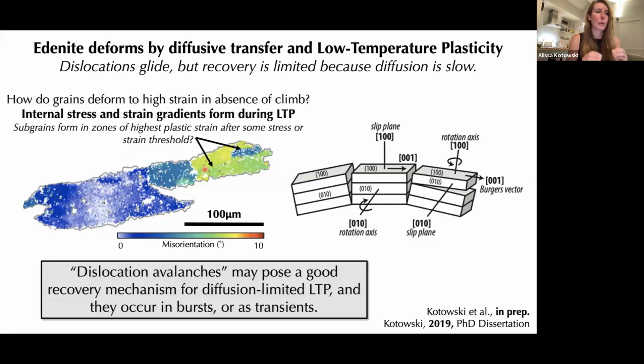So what this means ultimately is that we will have an imbalance in the number of dislocations coming in versus the number of dislocations going out. If it's hard for dislocations to leave, then they will come in, they will glide, they will hit each other and tangle, and you will actually create more internal stress and strain gradients as a function of the inability for dislocations to leave. So I think what this actually is showing us during this low temperature plasticity glide dominated mechanism is that we actually are producing internal stress and strain gradients as these dislocations are climbing through, or gliding through rather.